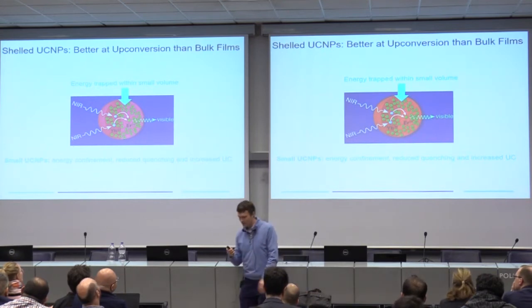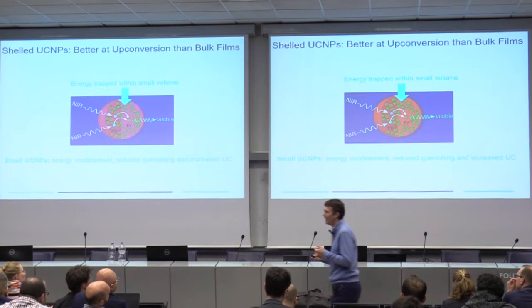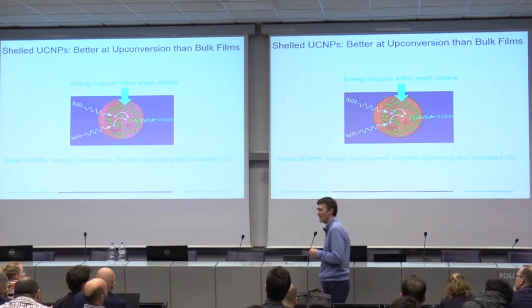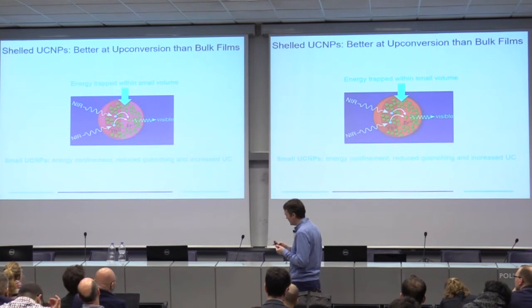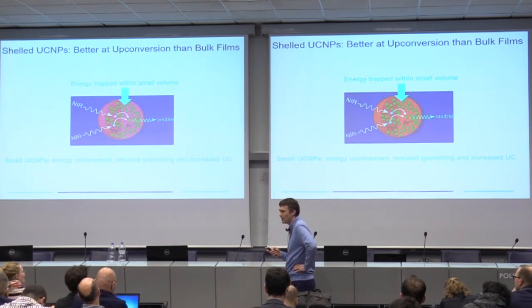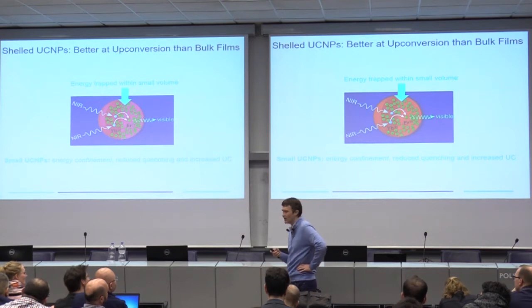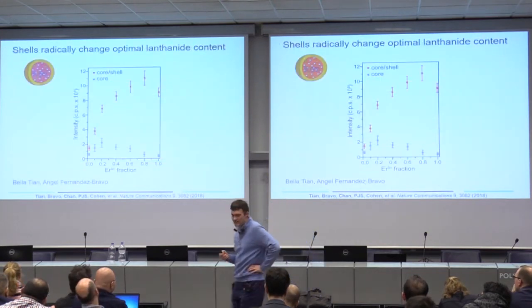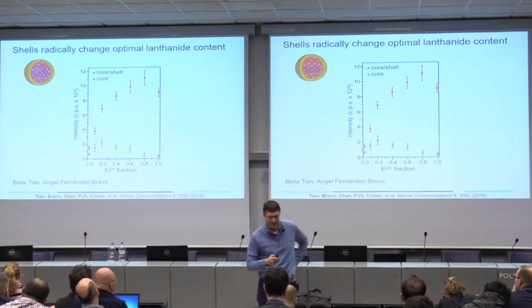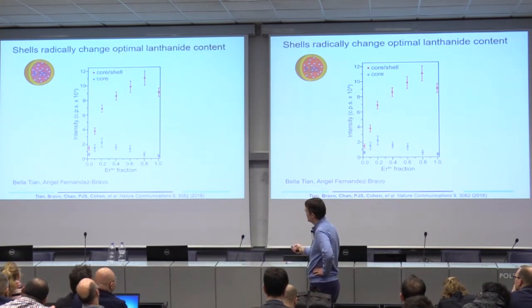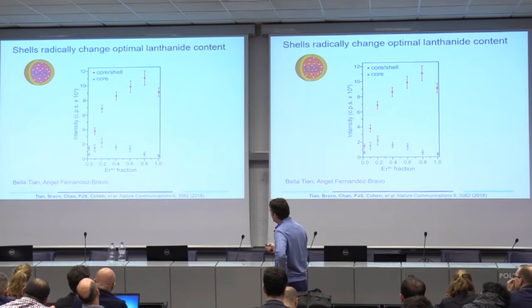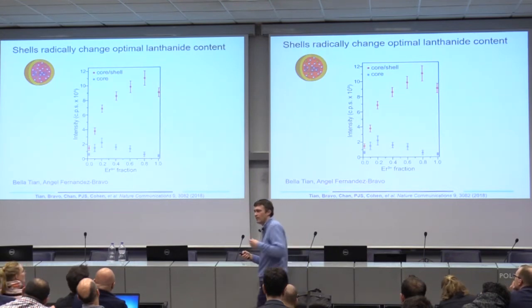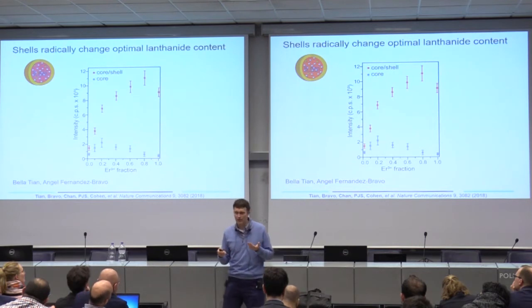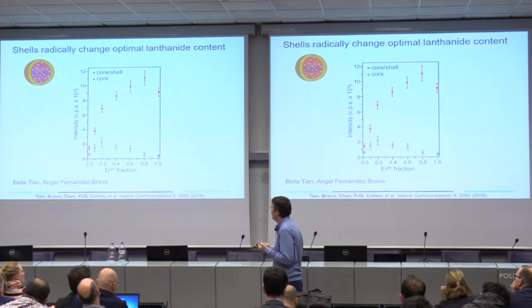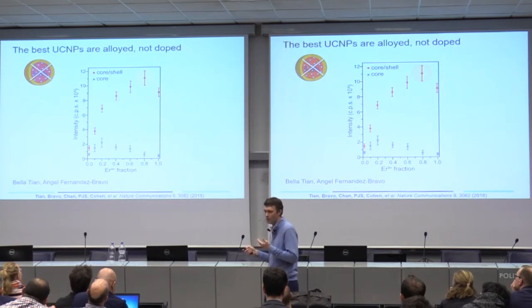And so this is a concept that is both simple and yet, for some reason, didn't really occur to most of the field for a while, including us. So once we kind of caught on, this has really made this field take off. So what this means is that if you take upconverters and you put shells on them, now your ideal concentrations, without shells, your ideal concentration was still actually a pretty small erbium fraction, at least for low powers. But now your ideal concentrations, in fact, they're not the ceramic doped with lanthanide. They're basically like 100% lanthanide particles, or well, as we call them, alloyed particles.